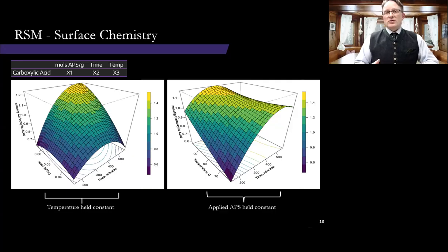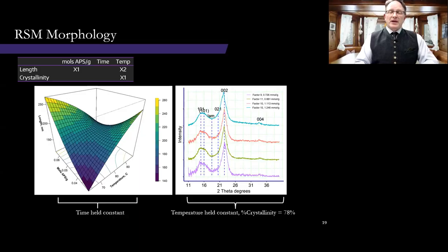These 3D surfaces allow us to hold one effect constant while evaluating the effect of the other treatments on our response. I applied this same technique to morphology, but if you recall from that first graph that I showed you with the way APS reacts, diameter was strongly affected by time, and it's a very fast hydrolysis reaction. So in all of the factors, there was no significant difference between each factor in our experiment. Length, however, statistical analysis showed that, again, ammonium persulfate applied had the greatest effect, with temperature a close second. Crystallinity, on the other hand, was only affected by temperature, and neither was affected by time.